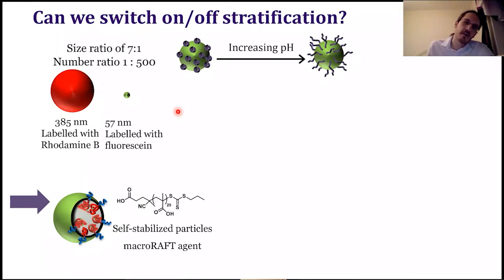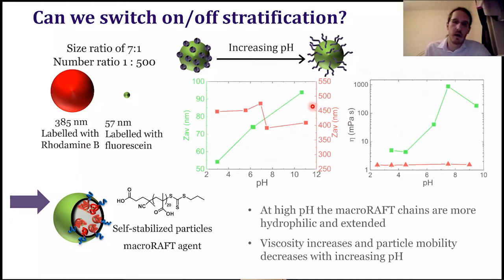So they have some polymer chains at the surface, which for low pH are collapsed. And for high pH, they extend, so their size changes quite a lot with pH. And we blend this again with the same large particles. And in this case, we also label green the small particles. So you can see here, this is the size of the small ones in green. When you increase the pH to about 10 or 11, the small particles double their size from 50 nanometers to 100 nanometers, and the large ones more or less remain constant.